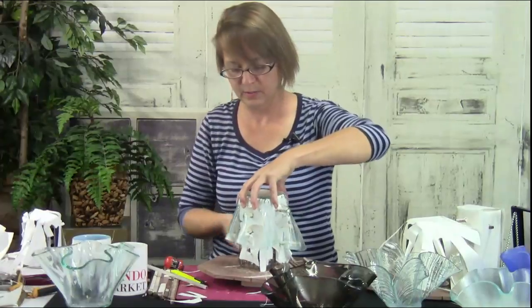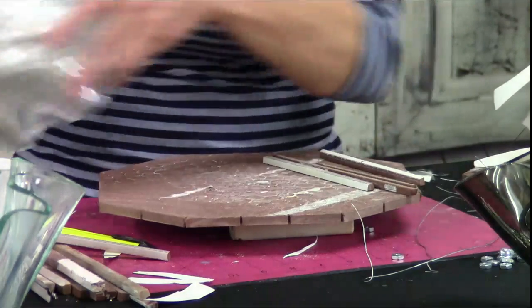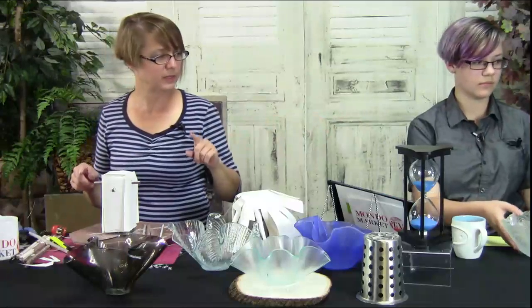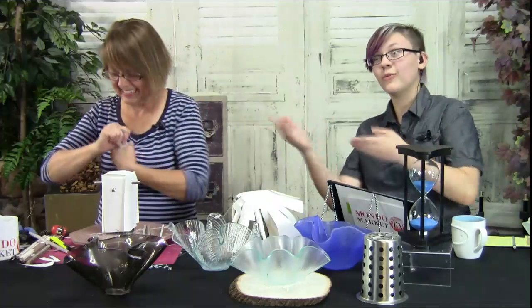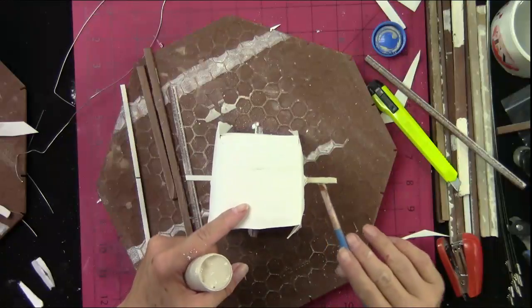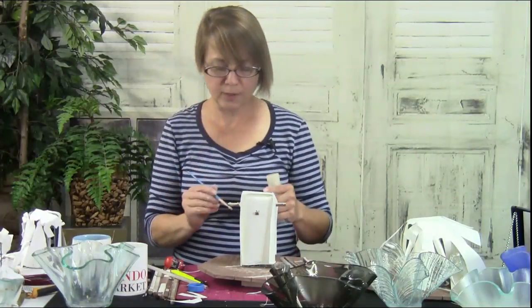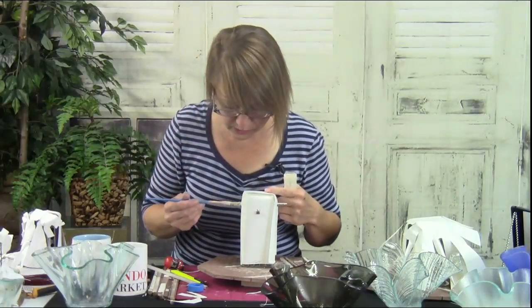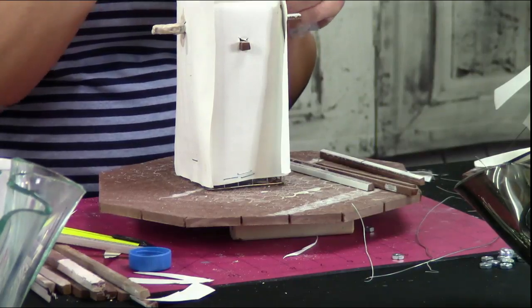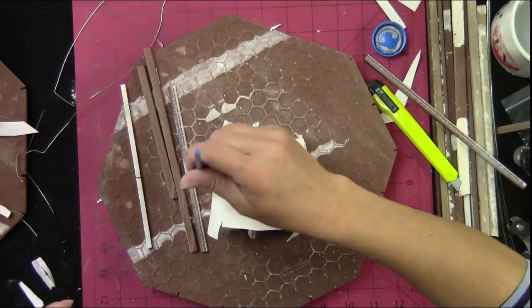Here's a fused and slumped version with all the pieces in it. Looking at the close-up, this one did make a mark. I actually covered these with bead release — bead release is the same ingredients as kiln wash but in different proportions, so it's thicker and crumblier. Knowing my glass is going to contract around this, I put a really thick coat on, hoping the glass would have a little bit of cushion. You could also probably wrap these in fiber paper — it didn't even dawn on me to do that, but you totally could.